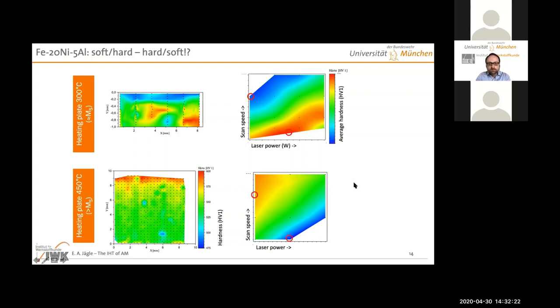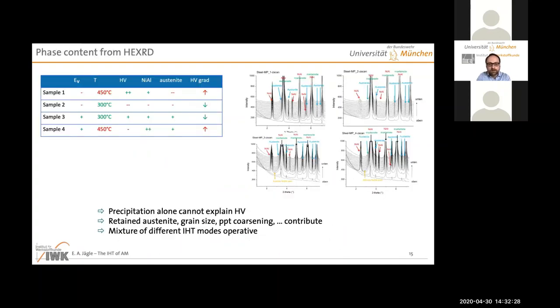We had a look at these specimens and gave them to our colleagues at the DLR, and they went to the synchrotron and did high energy X-ray diffraction. I think that was also in Grenoble, if I remember correctly. And we get a lot of things that we don't understand. We're trying to understand it at the moment, but if you just look at this table, with high energy density, low energy density, high temperature, low temperature, hardness, amount of NiAl precipitation phase, retained austenite phase, the orientation of the hardness gradient, it's all a bit of a mess. And we're still sorting through this data and trying to understand it, to be honest.